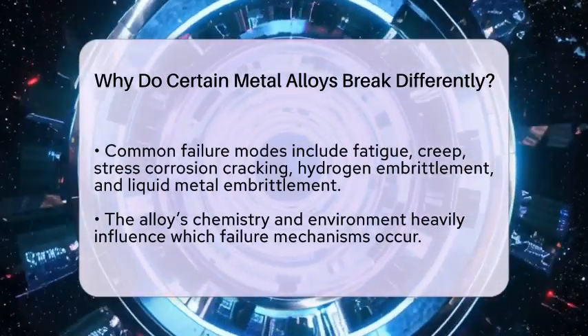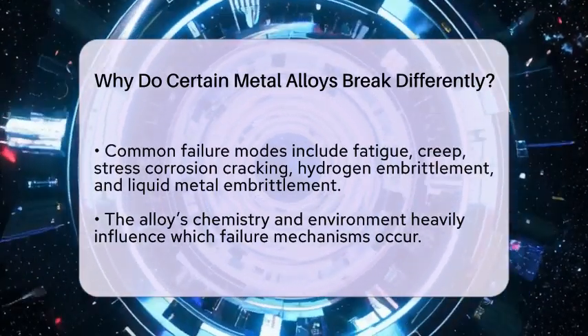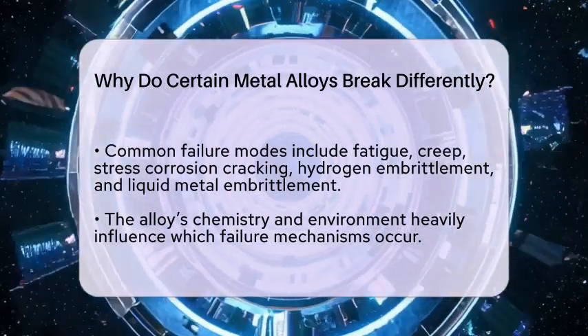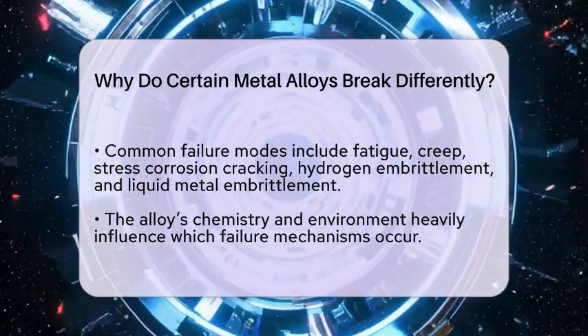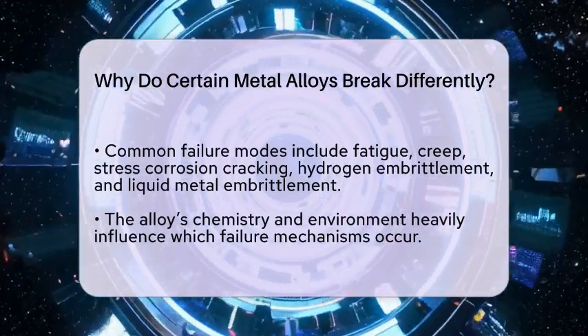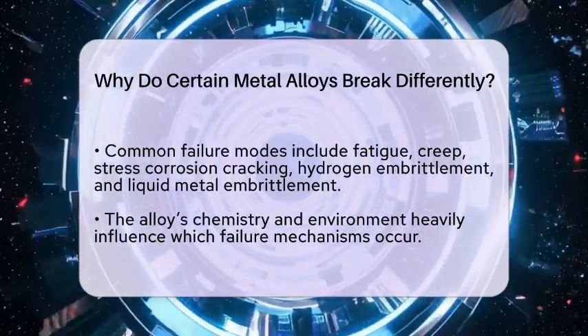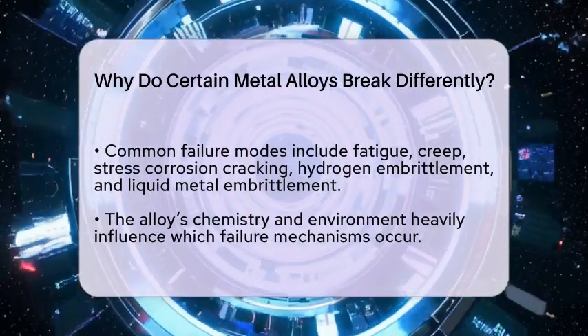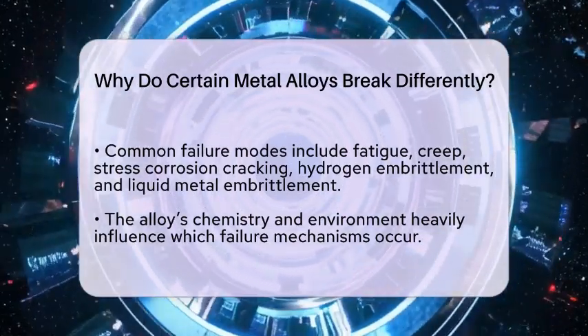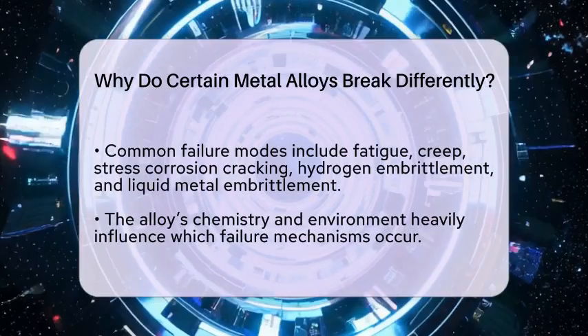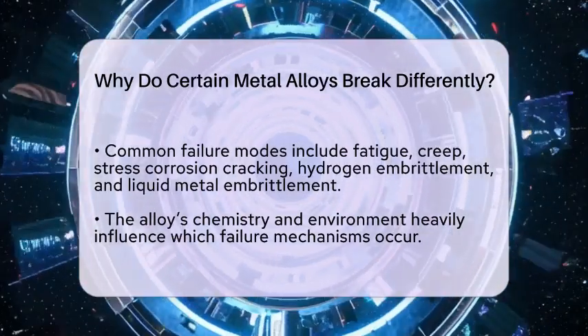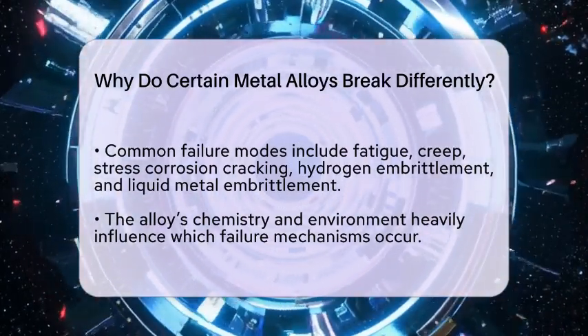Grain boundary characteristics also influence how and where cracks start. Some alloys have grain boundaries that resist crack growth, while others are more vulnerable. Cracks can propagate along grain boundaries, called intergranular fracture, or through the grains, called transgranular fracture. The chemistry and structure of these boundaries determine how easily cracks spread.